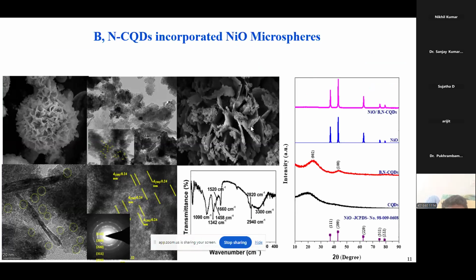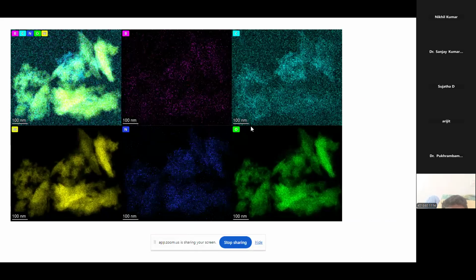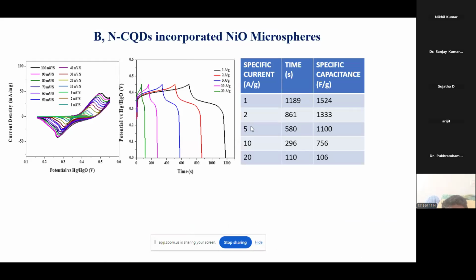We can match it with XRD as well, and TEM images like the SAED pattern. Then it shows the presence of nickel, BCNO in all the flakes. Then this is the supercapacitor application, which I coated on nickel foam and absorbed for 0.1 to 0.55. Then we got this GCD, and the specific capacitance value of 1524 we have achieved and reported.